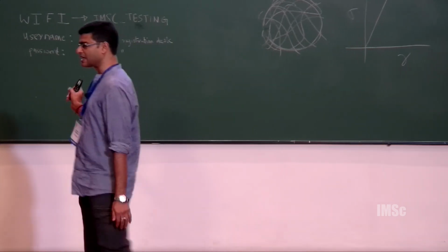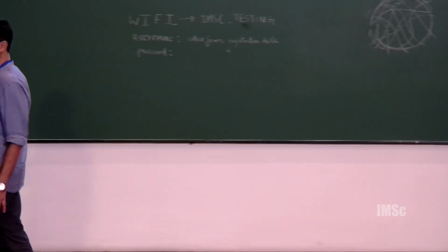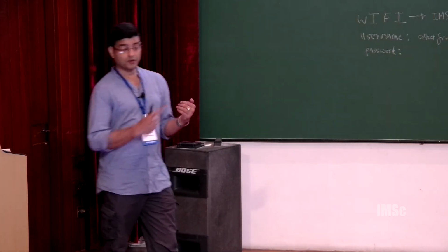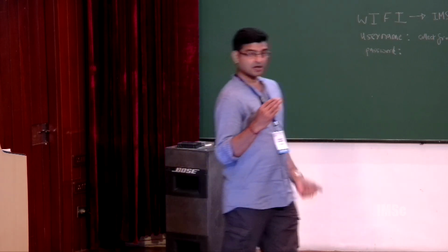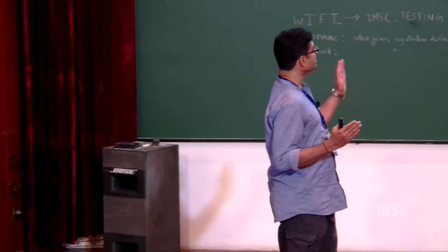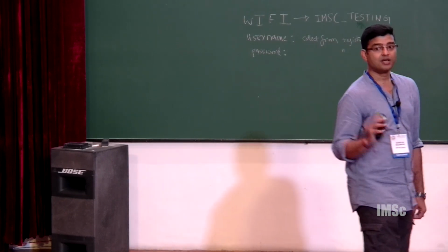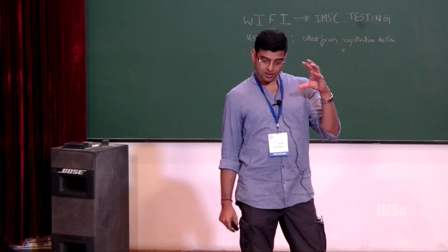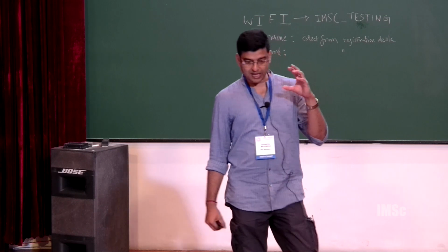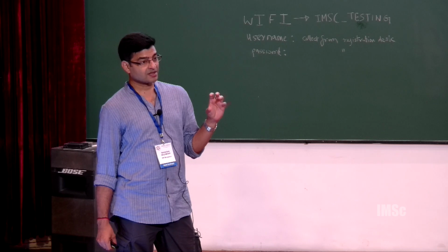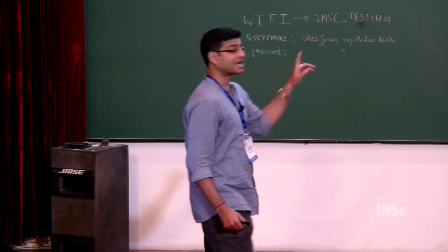I don't want to go into that, but this is a little complicated system. These are thermoresponsive particles. So if you cross a temperature, which is called the LCST, and for this particle it is around 32 degrees centigrade, the particle undergoes a transition to a smaller size. Actually, there is a reduction of size.